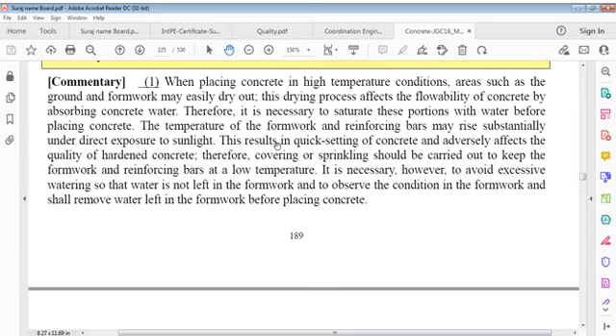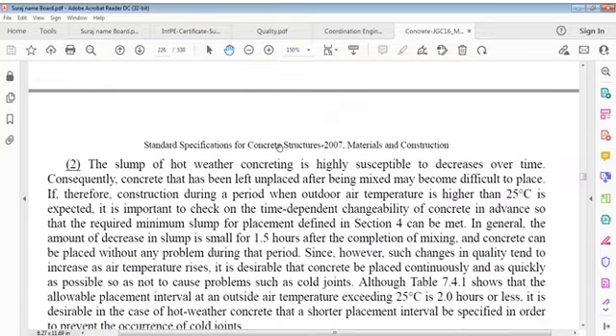Temperature of formwork and reinforcing bars may rise substantially under direct exposure to sun. This results in quick setting of concrete and adversely affects quality of hardened concrete. Therefore, covering or sprinkling should be carried out to keep formwork and reinforcing bars at low temperature. It is necessary, however, to avoid excessive watering so that water is not left in formwork, and to observe conditions in formwork, and shall remove water left in formwork before placing concrete.